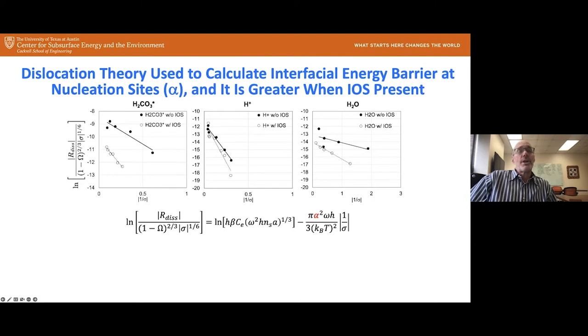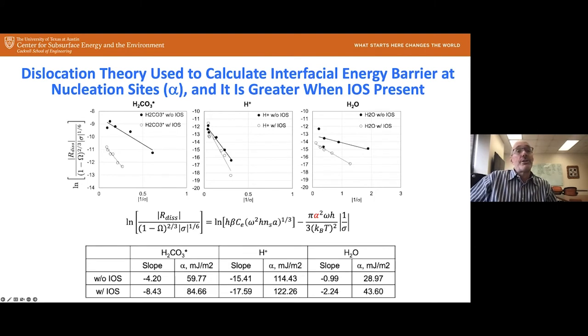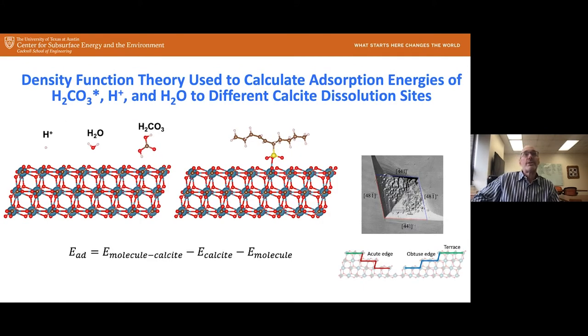And so we plot the results in a way that the model would allow us to. And what we get are these alpha values. And so you look at these alpha values, and whenever the IOS is present, we have a higher alpha value than we do when it's not. And so for carbonic acid, it's 84 versus 59, proton 122 versus 114, and water 43 versus 28. So that means there's this greater kinetic energy barrier, basically, or activation energy, that's necessary to promote dissolution in the case when we have IOS. That's a nice theoretical way of looking at it. It doesn't provide a microscopic insight, but it gives us a thermodynamic basis to think about it.